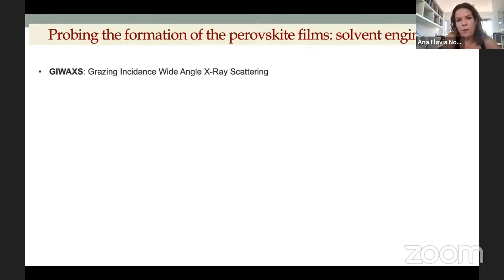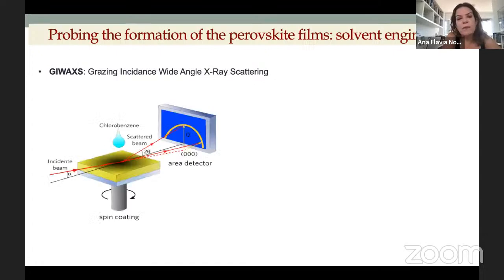Okay, and then we went to, what's the name of the beamline? I think it was X-ray 2, another beamline in the synchrotron, when we decided to probe the formation of the perovskite film. In this case, we did the GIWAXS, that is the grazing incidence wide angle X-ray scattering. So basically in this technique, this is your X-ray beam. This is your film here. This is the image that you can get in your 2D detector.